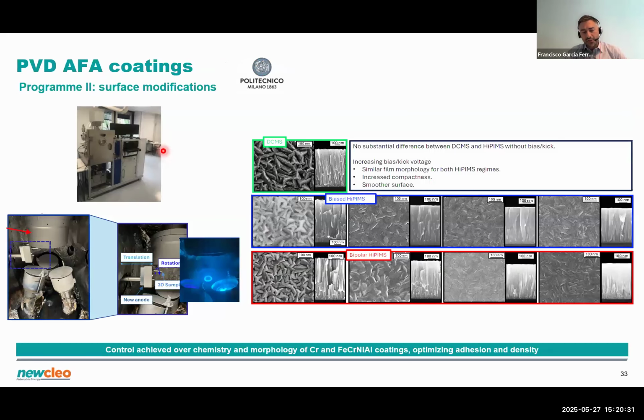So here I just want to show one possible example, a highlight of a PhD thesis work that Politecnico di Milano is carrying out, where we investigated PVD of a variety of compositions, but compositions rich in aluminum because this is known to perform well in lead. And so we developed this technique. We managed to control the morphologies, and we ran some ion irradiation tests and some corrosion tests.